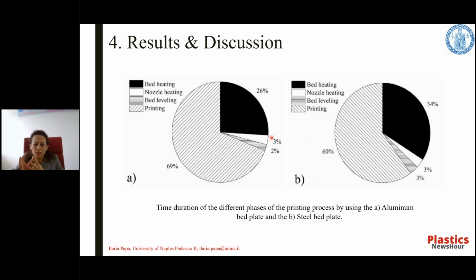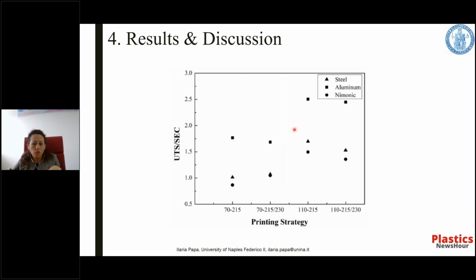Thus, in this part of the research, we have noted that it's better to use an aluminum plate for desktop 3D printers rather than steel plates, to reduce power and energy consumption of the FDM process, and this fact is related to the conductivity of the material, of course. From the values resulting from the energy consumption analysis, an analysis of the specific energy consumption, or SEC, was performed, that we can see in the slide, which is highly used in the literature as a key sustainable performance indicator. In particular, in the FDM process, SEC represents the energy consumption for printing the mass unit.